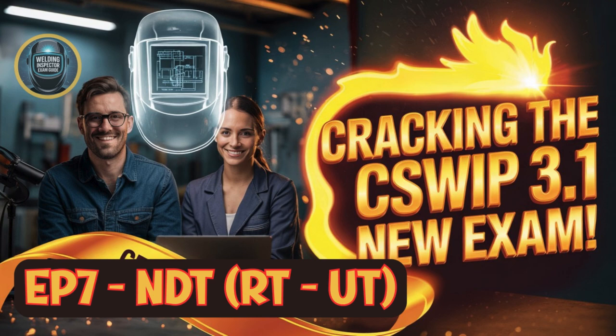Exactly. RT struggles with those planar defects, the cracks and lack of fusion, especially if they're oriented poorly. UT excels there. But RT is better for the volumetric stuff, like porosity. Generally, yes. RT gives you a good overall picture of porosity distribution, while UT might struggle to characterize it well. Portability-wise, gamma RT and manual UT are both pretty portable. X-ray units, especially powerful ones, tend to be less so.